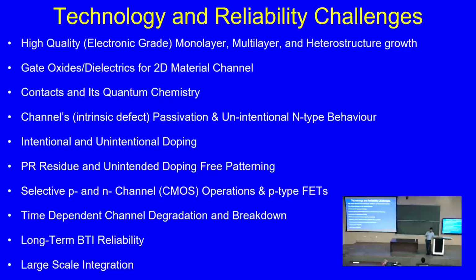But in 2D material, we found that there are two critical fields. One critical field for the breakdown, avalanche, and another critical field which results in a certain phase change across the channel, right? Now, how to avoid that phase change, for which you have to dig deeper and find why there is this phase change, right? Then long-term BTI reliability and large-scale integration. This is also something that we recently looked into.